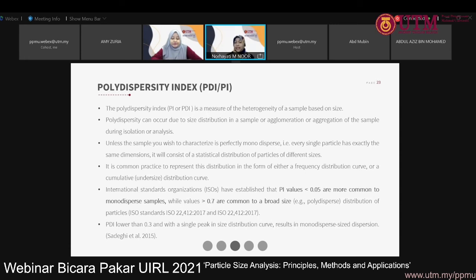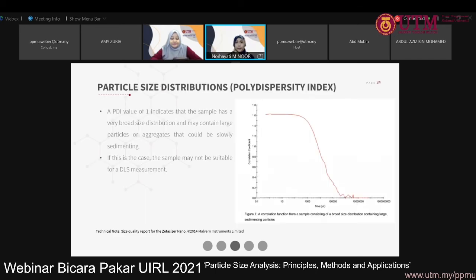But for the ISO standards, a PDI value less than 0.05 is called monodisperse. But if the PDI is 0.7, you have a polydisperse sample, meaning you have many peaks, so it is a broad size distribution. Mostly in pharmaceuticals and skincare formulations, we target a PDI lower than 0.3. A PDI indicating a very broad size distribution, more than 0.7, means that your sample is not suitable for DLS to measure the size.